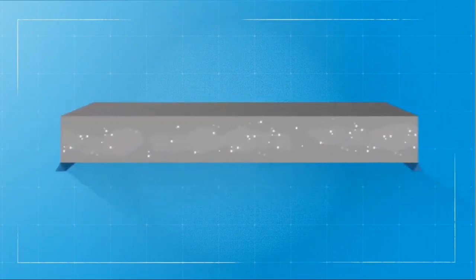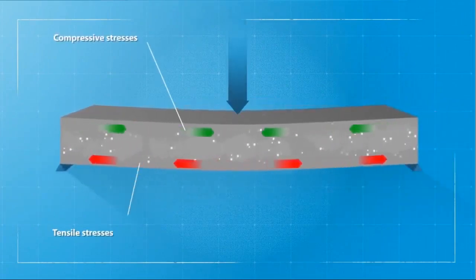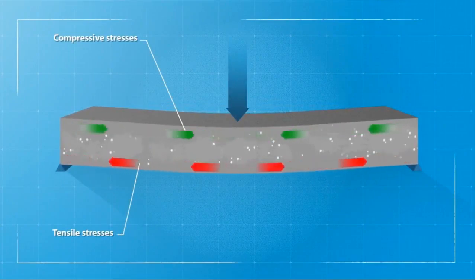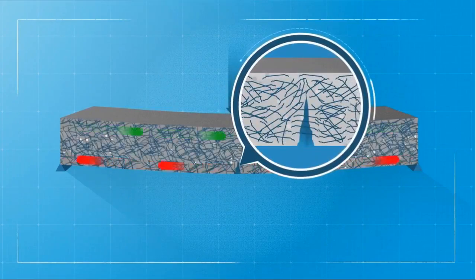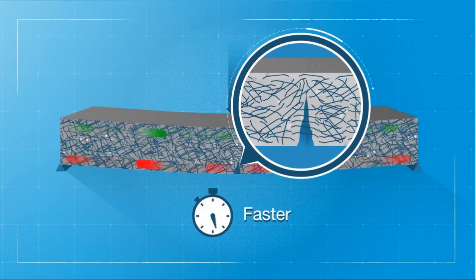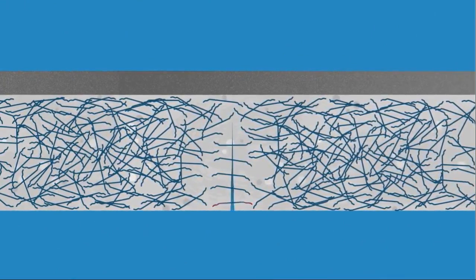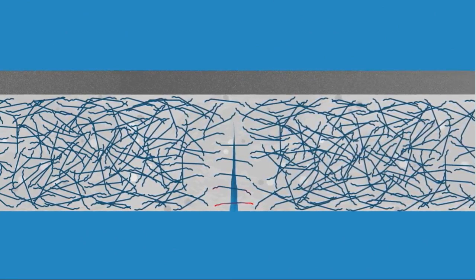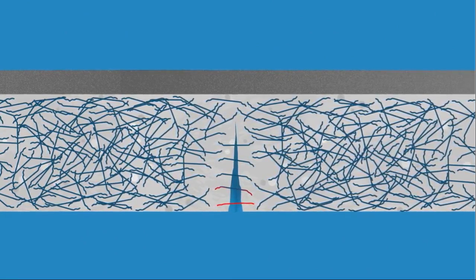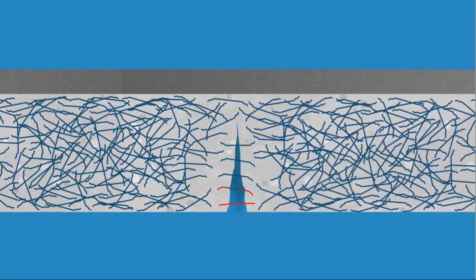Take a random concrete structure. When subjected to loading, compressive and tension stresses start to build. Over time, small cracks will appear in places where the stress reaches a critical point. Steel fiber interacts within the concrete matrix, absorbing tensile stresses at any point and in any direction. As a result, steel fiber picks up small cracks much faster than traditional reinforcement. When a crack occurs, the hooked ends of the fibers remain solidly anchored on each side of the crack, acting as a stress transfer media. Once the maximum bond strength with the concrete is reached, the pull-out takes full effect. This enables the next fiber to take over, delaying cracks from growing.